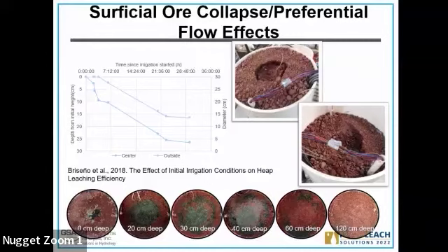At the bottom, this is after a certain time of irrigation, and then we applied the dye into the column. We also found that with greater depth, you can see what actually escaped to the central area where the consolidated area was avoided, and what actually went around. It proves there's a preferential flow that occurred due to this. And again, you are not wetting this ore properly.